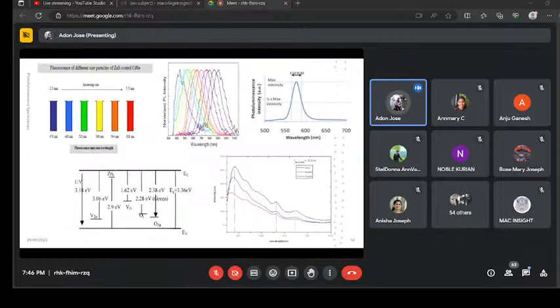On this slide I have provided the variation of cadmium selenide quantum dots. We can see that whenever the size of that particular material is increased, its emission, its luminescence that we have observed also varies. That means whenever the size changes, the light emitted from the material changes. That means we can calculate its energy difference or band gap from these kinds of materials by simply using the equation: the energy gap E equals hc by lambda.